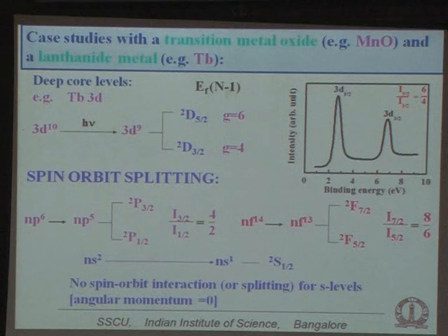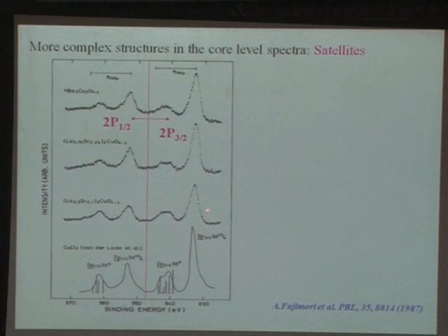Just like here. So copper oxide, let's look at some copper oxides. What we see is 4 peaks. And I have an approximate separation that these are all related to 2p3/2, these are all related to 2p1/2. For some reason, each of the spin-orbit peaks has a partner, and we call them the satellite. I think this is copper chloride, so it's not only an oxide. This is strontium copper oxide. This is intermediate copper oxide. You take CuO, anything you take. Copper 2+ state, you will have these two peaks. But if you take copper 1+ state, you will not have this.